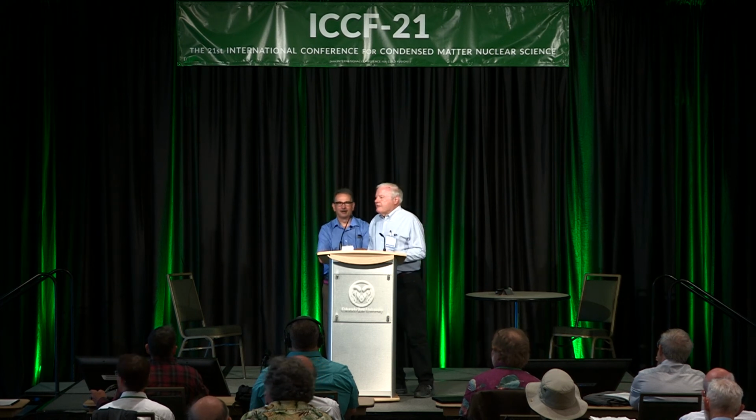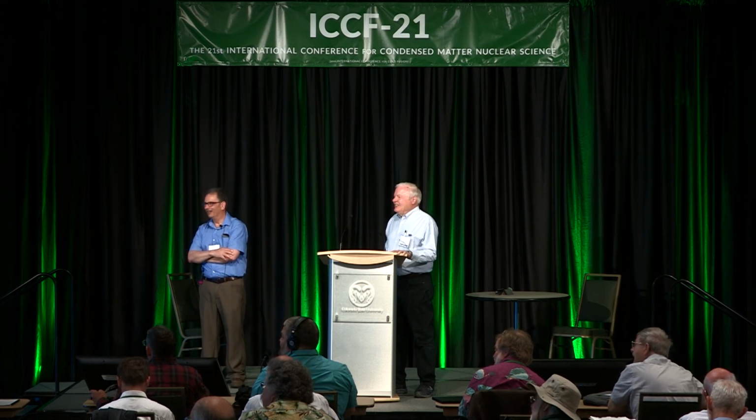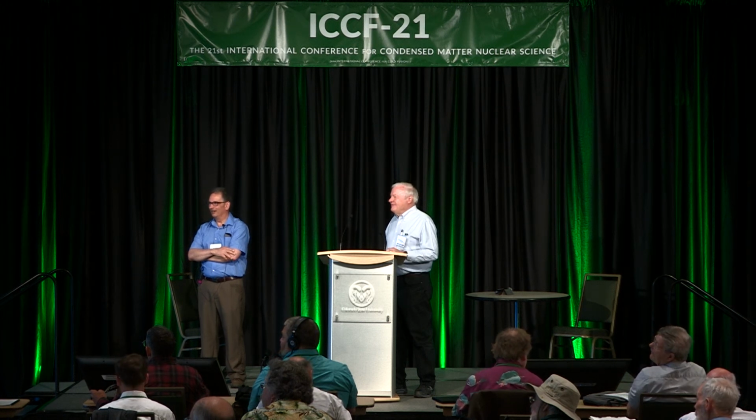I'm sure Francesco has a quick question because he wants time for his presentation. First one, good paper. Second one, we have long experience with pulsing palladium wire, and we found that the surface temperature is really larger than that of the bulk because of skin effect. Do you have an idea which one is your surface temperature? In the nickel? Yes. Where you give the pulse, sure. Well, because nickel is ferromagnetic, it has the skin effect, so most of the current is going at the interface. But this is just plasma sprayed, so it's very random. There's no controlled morphology or anything. Okay, thank you.